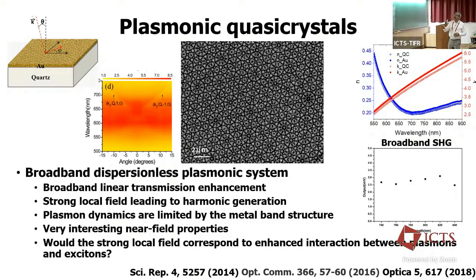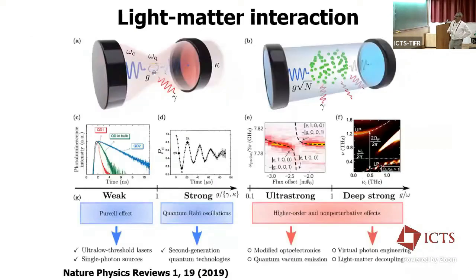They can couple to each other, and you can have mode hybridization and other things. But the important point is that you have a strong local field at these interfaces, and that can contribute, combined with the weak nonlinearity of the gold itself, and we showed that we can have broadband second harmonic generation from these structures. Because it's a thin film nonlinearity, there is no phase matching angle requirement in this case.